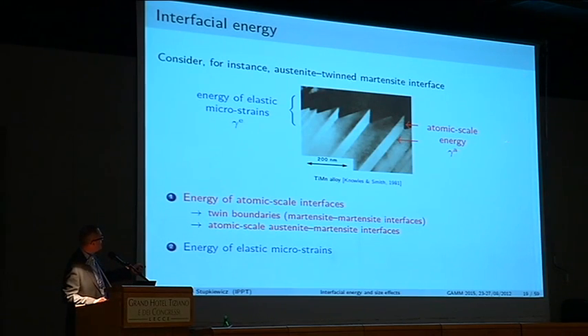So the first one, those in red with the index A, gamma A, would be the atomic scale energy, and here we have two kinds of interfacial energy, namely the energy of twinning planes. We have several twinning planes separating individual twin variants, martensitic variants, and each interface can be understood as a kind of defect in the crystallographic lattice. So the twin boundary energy can be seen as the energy of the defect in the crystallographic lattice. On the other hand, there is also the direct interface between martensite and austenite, and this is also at this level an atomic scale energy, probably higher than the other one, and these are the interfacial energies that we wish to get from material science or computational material science. We will take them for granted. We don't know very good values for these parameters, but we have some estimates and we will use these.